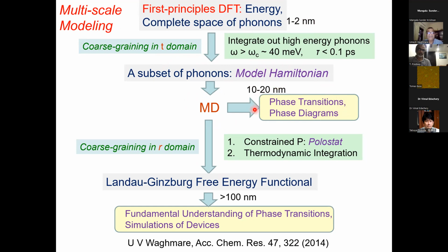But this is still not enough to access modeling of devices or technologies based on these materials. So we take the next step, where we do coarse graining in the real space domain. And the technique we use is called the Polostat, like thermostat, combined with thermodynamic integration, which allows us to derive the Landau theory or Landau-Ginzburg theory free energy functional from first principles essentially. And that allows us to now simulate devices on the scale of hundreds of nanometers. And at the same time, we derive a fundamental understanding of phase transitions, as well as get the capability of simulating devices based on these systems.